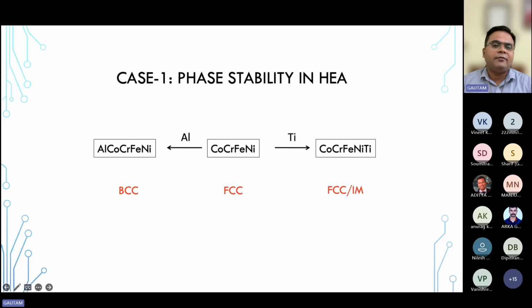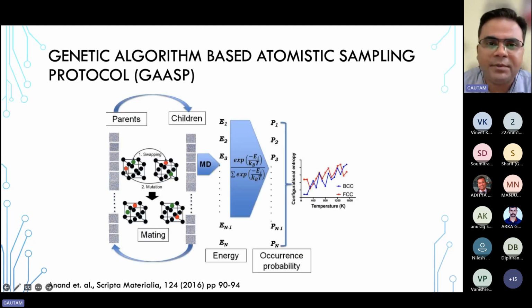Of course, if you have, say, 0.5 aluminium with cobalt, chromium, iron, nickel, it still shows FCC, and there is a gradual FCC to BCC transition. And with titanium, you just find intermetallics in addition to FCC. So that was the problem we had in hand. Can we use this approach? So we developed this method, which we called the genetic algorithm-based atomistic sampling protocol. It has a few components to derive the configurational entropy.